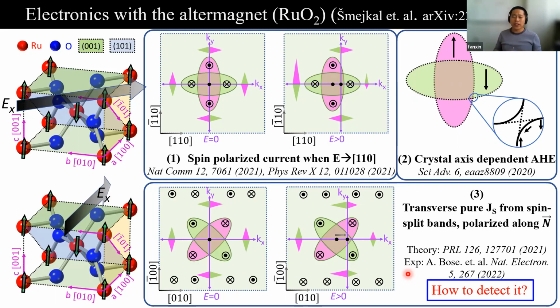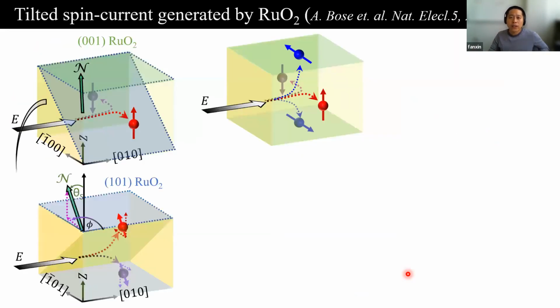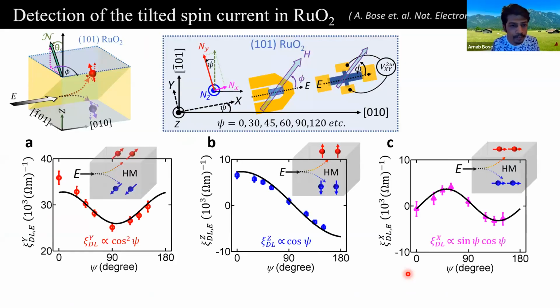I see. So if I call this the effective spin Hall angle, it's not that large. Yes, it is not extremely large. I would say it is nearly 1 order of magnitude smaller than platinum. One of the possibilities that we think could be the cause is domain cancellation, because here the origin is the time-odd spin current. If it is in the multi-domain state, then we'll have a reduction of the spin current. That's why we probably have a nearly 1 order of magnitude lower reported value of spin current than the theory predictions. But that is one of the possibilities.